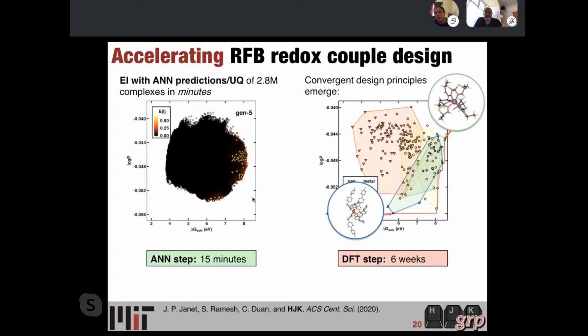If we want to make a sacrifice on the redox potential, which is what is shown on the x-axis, we can get better solubility if we go to really bulky ligands, but that's actually perfectly in line with what I mentioned at the start, that redox potential is very heavily tuned by size, but it turns out one great way to improve solubility is by adding just bulkier groups. And so that's part of why there's this challenge and this trade-off in how we're optimizing these materials.